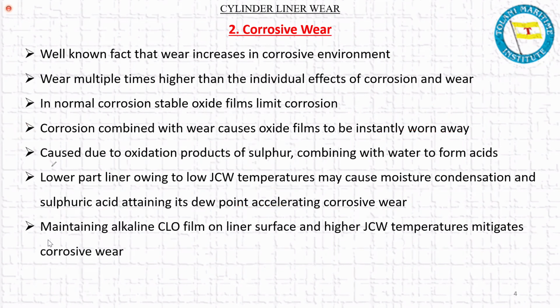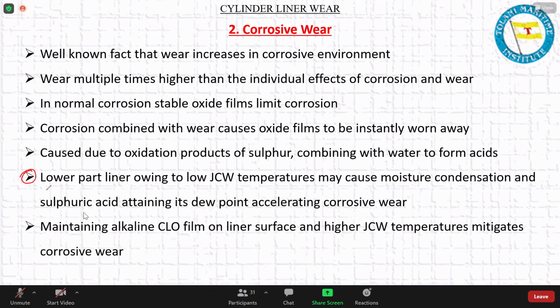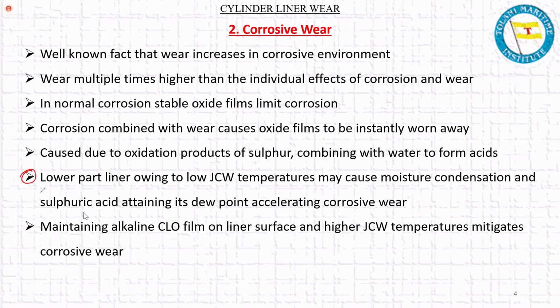Please remember that corrosive wear is not just taking place in the upper part of the liner, it is more prone to take place in the lower parts of the liner, because at the lower end you have low jacket cooling water temperature, low liner wall temperatures, low exhaust temperatures and all. So there are chances that under these low temperature conditions there will be some moisture condensation, and those sulfur trioxides will combine with water to form sulfuric acid, and this sulfuric acid will reach its dew point and settle down on the liner walls. And this will cause an acceleration of the corrosion taking place. Is this clear? Yes, sir.